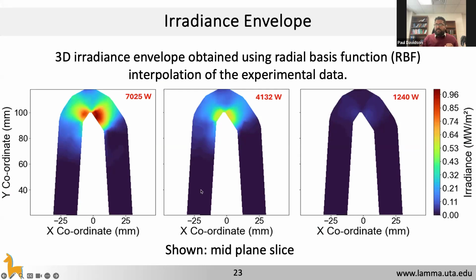And we do that using radial basis function. So we take the measurements we have made, fit the whole thing using radial basis function, and create a 3D irradiance profile. The white region in the middle is the quartz block, and the colored region is essentially the flux profile which you get. This is all taken at midplane, but you can imagine that we can do it for any plane within the quartz block. So this is the profile of radiation which we get for 7,000 watts, 4,000, and 1,200 watts.